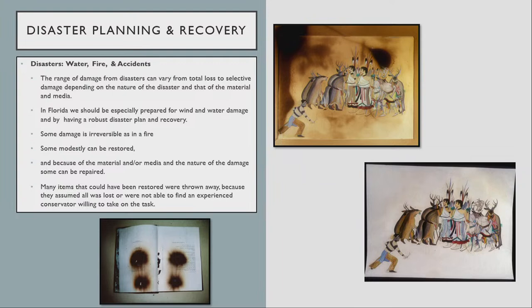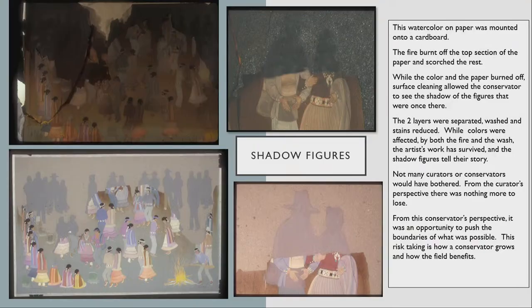Some, in the book below, irreversible were the damages. Some damage can be restored, as the image you'll see on the right. It was in a fire, paper burned, and there's soot and discoloration, but it was able to be restored. And because of the materials or the media, the nature of the damage can be repaired in some cases. Many items that could have been restored were thrown away because they assumed all was lost or were not able to find an experienced conservator willing to take the risk in attempting. My theory is if you think it's so lost, give it to me and it costs nothing to find out what we can do. So here's an illustration.